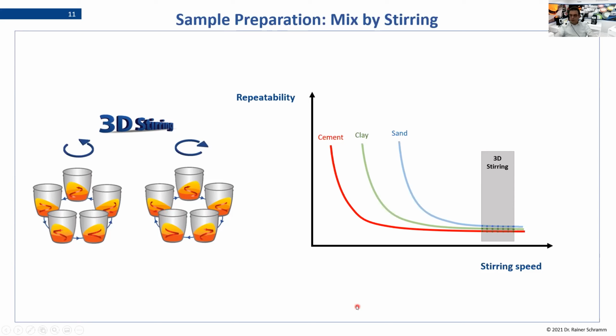And we made a bachelor thesis to find out what the optimal agitation speeds are for the different applications. And it was very clear that there's always a kind of limit where underneath it would not work. And if you go over it, then you get very homogeneous melts and then also high precision beads. And so we could already save in the system, for all the different materials, the agitation speed which is optimal.